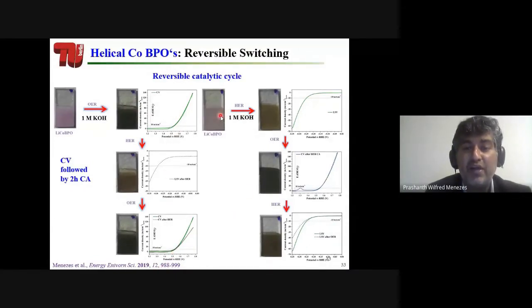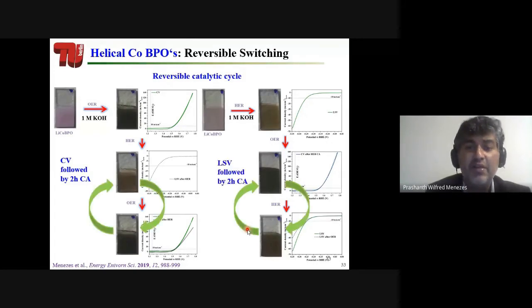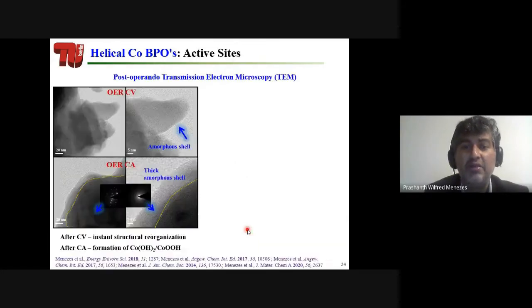Similarly, we can also do it for hydrogen evolution reaction. You take the catalyst, apply your potential, you can form this black colored film, which is equivalent to this one, and then you can reversibly produce it. So technically, it means that you can use your catalyst both at the anode and cathode. That's it. So this is clearly shown here. But important thing is that we don't lose any activity even if you switch the electrodes. This is the take-home message.